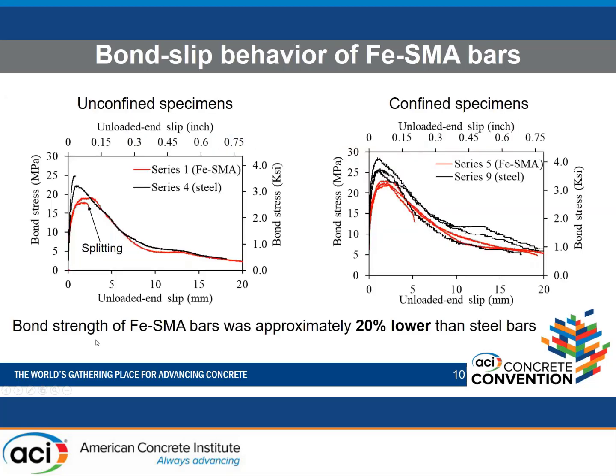So now I will show the bond slip versus bond stress for the different test series. And for your convenience, I'm presenting the bond stresses in both megapascal and KSI, and the slip in both millimeters and inches. First, I will show the comparison between the SMA bars with no heat activation versus conventional steel bars. This will be our benchmark, just to see how close or far the behavior is between the SMA bars and the conventional steel bars. And looking at both unconfined specimens and confined specimens, we can see a very similar behavior between both SMA bars and conventional steel bars.